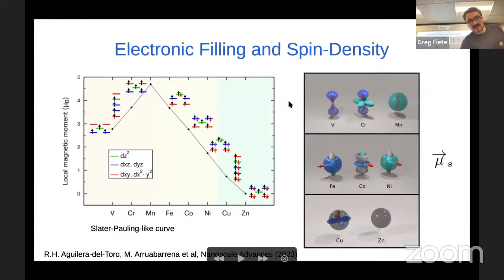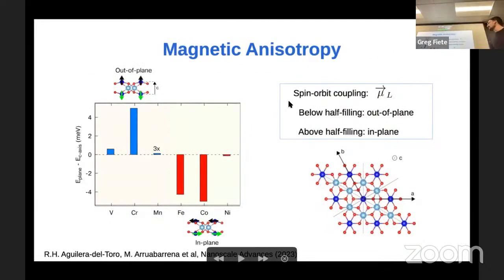So we will move now to the actual anisotropy. We did it similarly to the previous case. We studied whether the compounds prefer to have the spins outside of the plane or aligned in the plane for the different ilmenites. And we find a quite nice trend: below half filling, the anisotropy wants to be out of the plane, and above half filling, it turns in plane. Some compounds like chromium have a large magnetic anisotropy, also iron and cobalt, while for others the anisotropy is smaller. Also, when we are inside the plane, the spin orientation was always one of these equivalent directions.